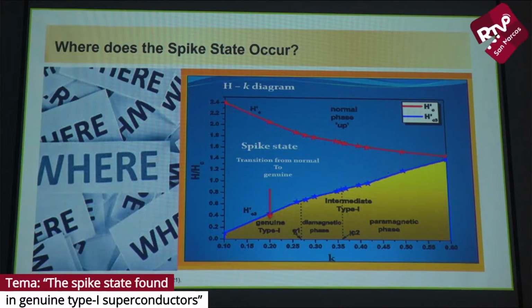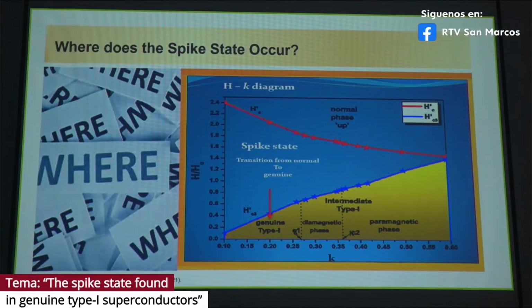When you're decreasing the applied magnetic field, all the magnetic field in the normal state is quantized by the supercurrent around the edge of the sample. At the surface of the needle, currents are created, and they quantize the magnetic field inside, forming vortices. Okay, but you divide this into the intermediate type 1 and the genuine type 1.